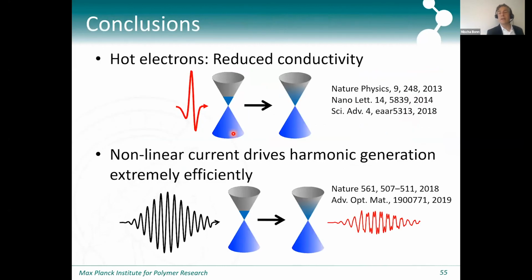So with that, I'd like to conclude, and I hope I've shown you that hot electrons in graphene exhibit a reduced conductivity, which is good and bad. It's bad in the sense that it's going to be very difficult to make a very fast, small field effect transistor using graphene. It's good in the sense that you very quickly reach a nonlinear regime where you can then use the nonlinear currents to generate high harmonics extremely efficiently.